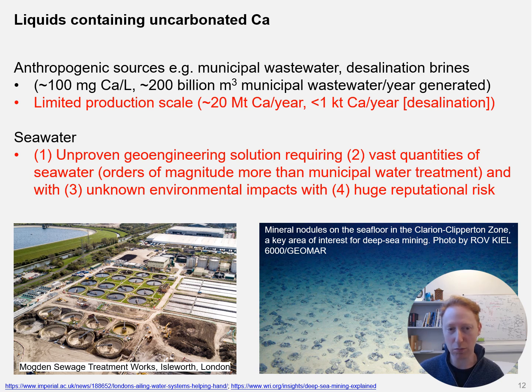Seawater carbonation is much more problematic. We would need to apply carbonation of seawater at orders of magnitude larger scale than we currently treat municipal wastewater. So this would be a really, really large industry that we would be generating from scratch. It is an unproven solution. The environmental impacts of seawater carbonation at mass scale are unknown, and so it also carries a huge reputational risk. And that's the reason why I've shown the seafloor nodules image on the bottom right, since there has been huge opposition to mining these resources due to their unknown environmental impacts. To me, it seems really difficult to envisage how seawater carbonation would be a practically viable solution at the gigaton scale anytime soon, if at all.